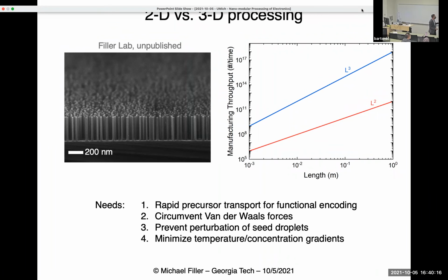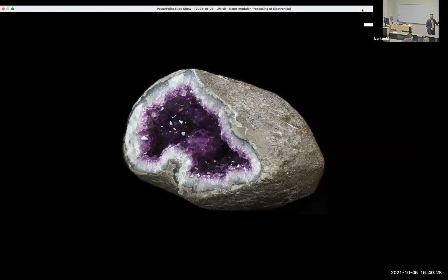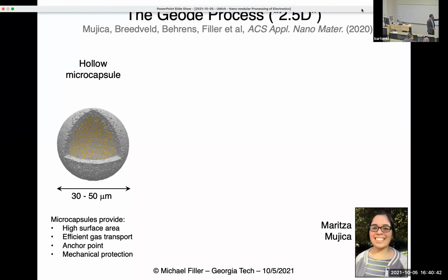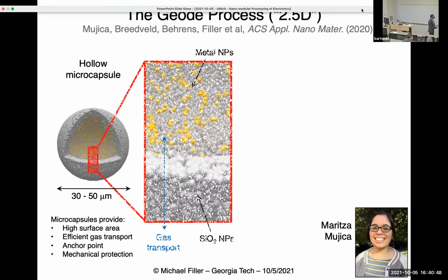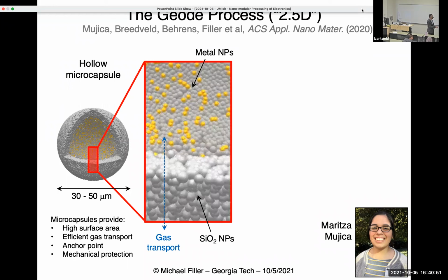Okay, so we are working at finding a way to go from 2D processing to 3D processing, or as close to 3D processing as we can to get that productivity enhancement. And we developed a process we call the Geode process after geodes. Right? Geodes are rock formations where you have crystallites that grow on the interior of some kind of rock. And we're doing that, but our geodes are 30 to 50 microns in diameter. Okay. And they are porous walled. And we line the interior with the little seed particles that drive nanowire growth that I just showed you a bunch of pictures of before.